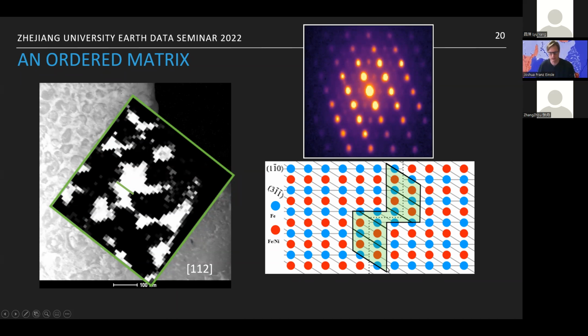as you see here in this green region, are areas where we end up with slightly more iron than what would be expected for the crystallographic structure that we expect. This is what's called an antiphase boundary, because it's a slight defect. You can see that this region up here doesn't quite align with this region down here, but it creates these. We expect these antiphase boundaries about every 10 to 12 nanometers in the matrix.